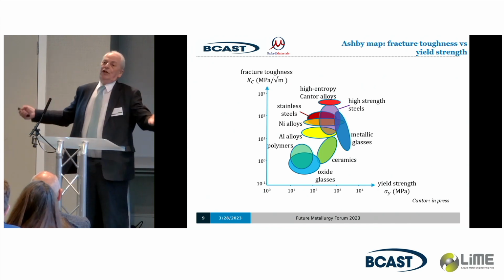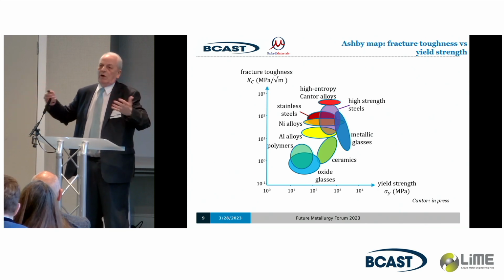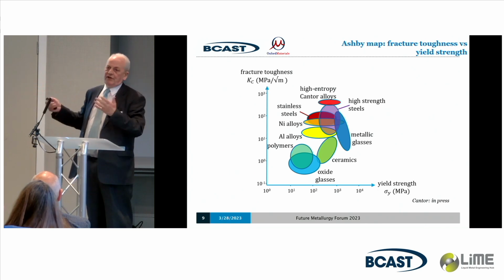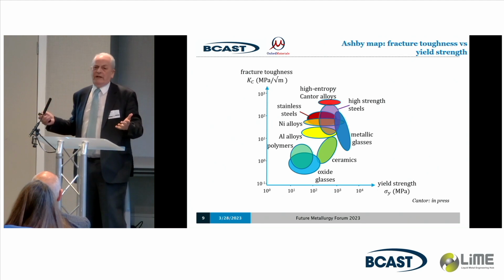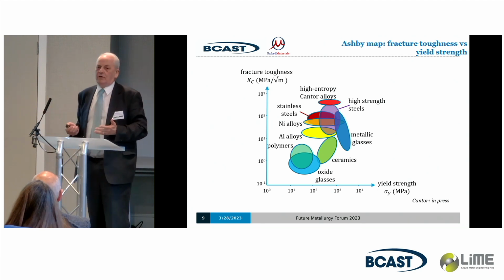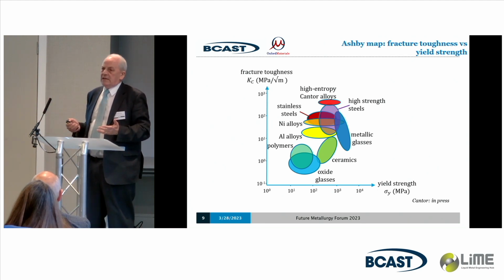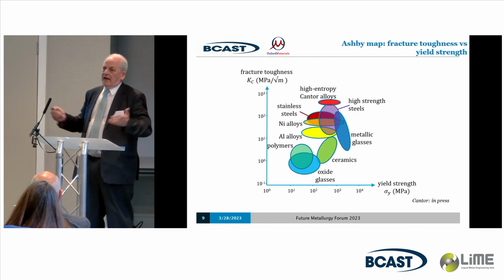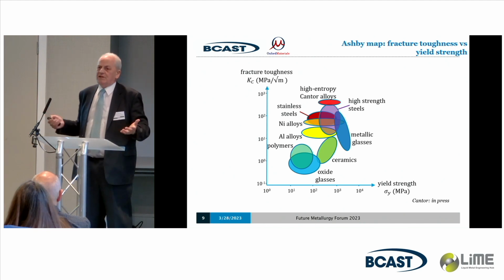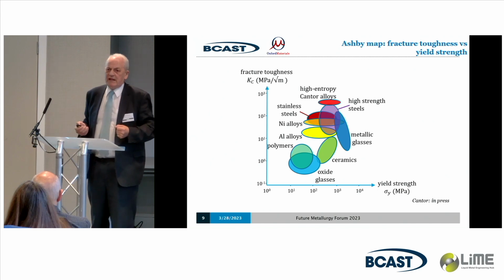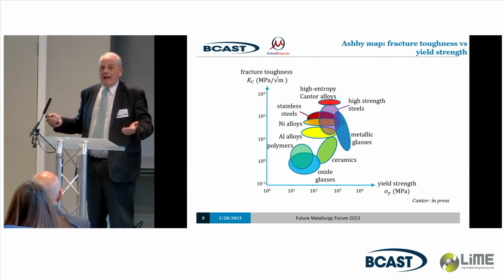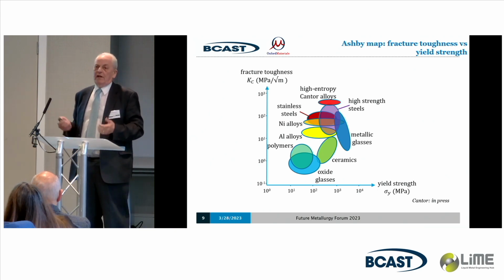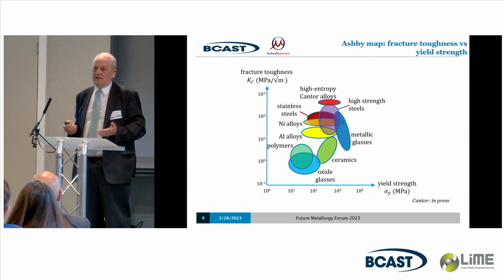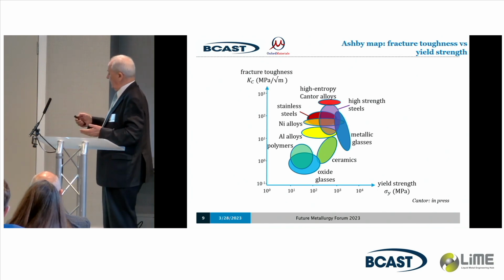By the way, there are lots and lots of, in quotes, Cantor alloys, the original one and modified compositions. I'll show you in a minute how many there are. There are millions and millions of them, way more than we've even looked at yet. They all have ductilities of 50 to 100%, even 120%. But they have strengths in the 0.5 to 1 gigapascal, even up to 1.5 gigapascal size. And that beats pretty much anything, as shown here.